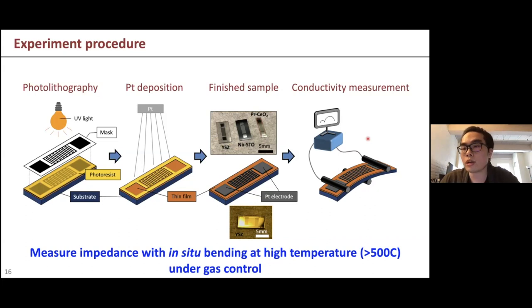And in the end, I will conduct the conductivity measurement with the applied strain, all at the same time. So basically, in short, I'm going to do a conductivity measurement at high temperature with gas control, because some functional oxides are mixed conductors, and they can exchange oxygen with the atmosphere, which will change their carrier concentration. And then also I want to apply the strain in situ, because with some techniques, you can create strain at room temperature and then just raise the temperature. However, due to thermal expansion and other factors, I don't think that's a very good technique. So what we want to do here is actually apply the strain in situ under the operation condition of the functional oxide. So there are a lot of things we have to do at the same time.